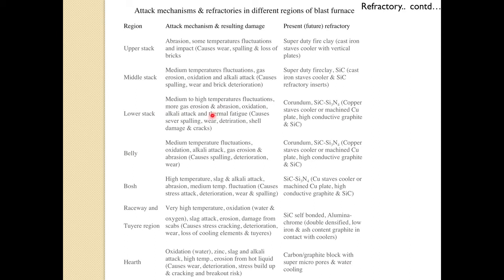Gas erosion, abrasion, oxidation, alkali attack, and thermal fatigue occur in the lower stack region. Corundum, silicon carbide, silicon nitride refractories with copper stave cooler or machined copper plate are required here.